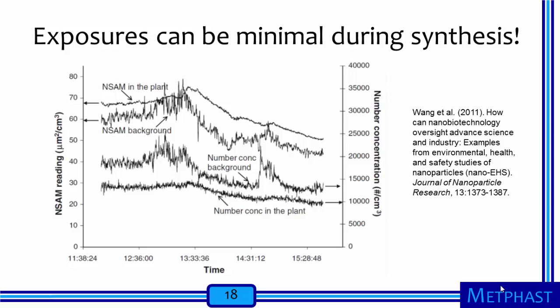It should be emphasized that each of these examples that illustrate potential worker exposures is a unique situation. Each workplace and process step is unique. There is evidence that nanomaterial synthesis on the production scale can be operated with no apparent increases in general particle levels. For example, Wang and co-authors compared particle surface area concentration and number concentration readings in a silicon nanoparticle production facility over a 4-hour period as nanoparticles were being synthesized, to background concentrations outside the work area. The measurements were essentially the same inside the work area as outside. With proper process design, operating procedures, and engineering control measures, worker exposures can be minimized.